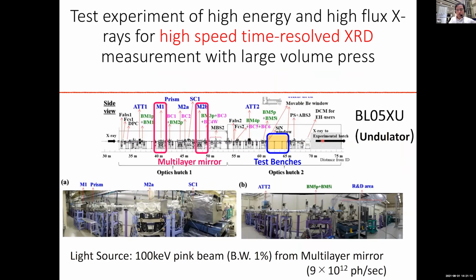I also conducted a test experiment of high energy and high flux X-ray for high-speed time resolved XRD measurement with a large volume press. This experiment was done at BL05XU, an undulator beamline installed with a multilayer mirror. It can generate a very high energy pink beam of 100 keV with a bandwidth of about 1%. I brought the press to this beamline for a test experiment of high speed time-resolved XRD.